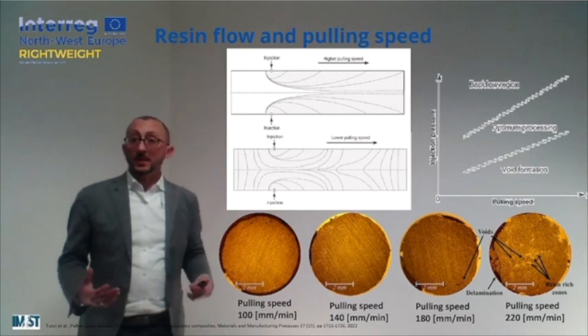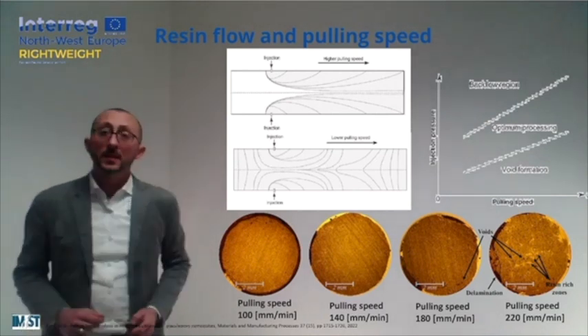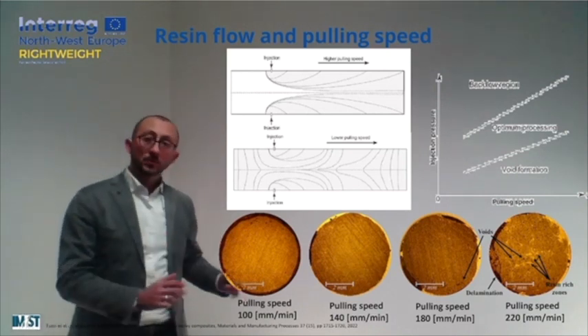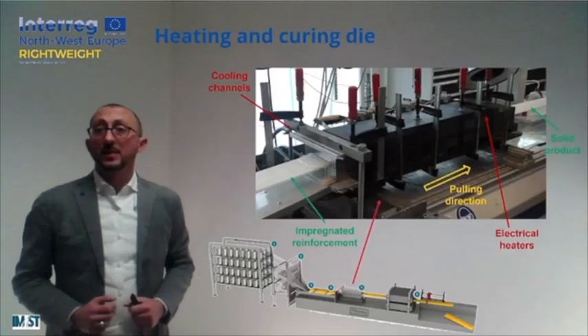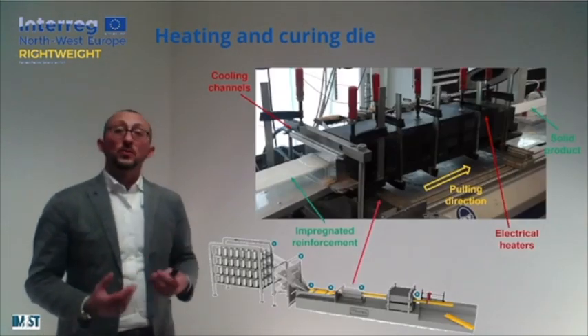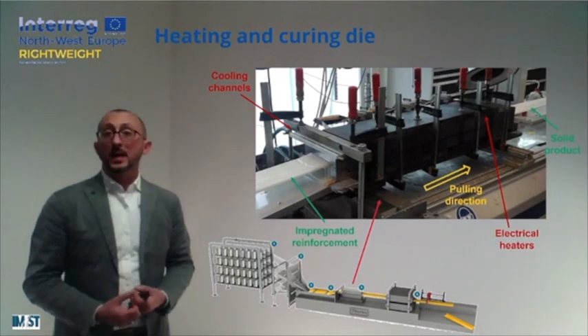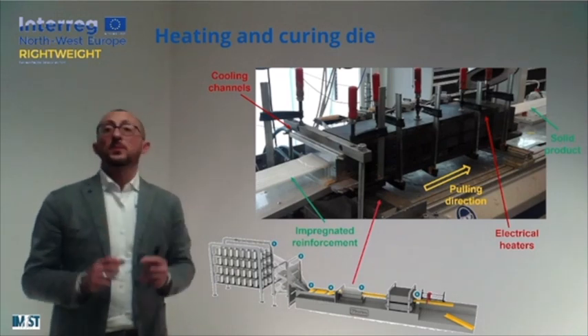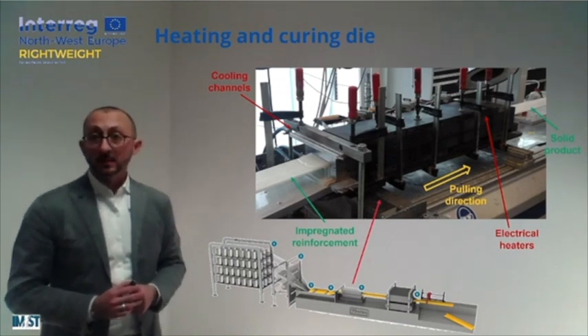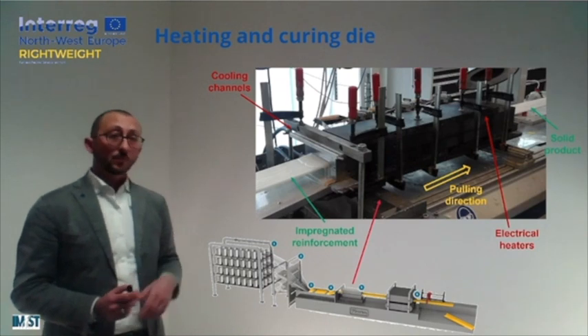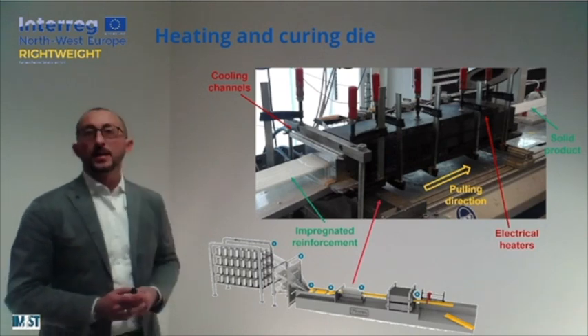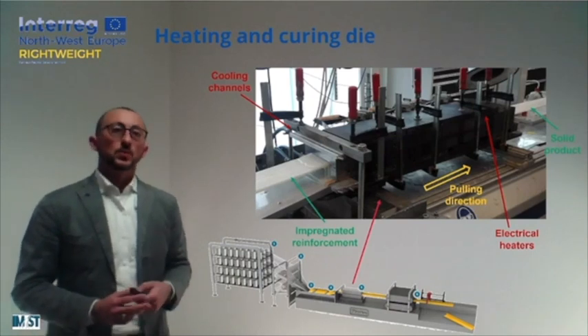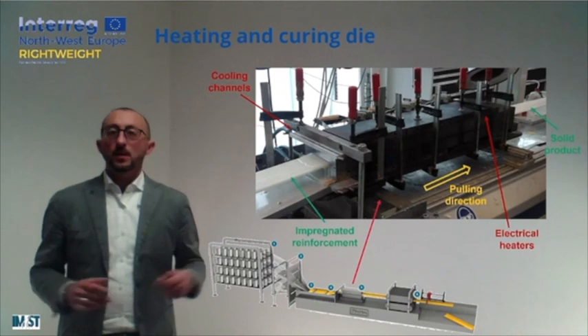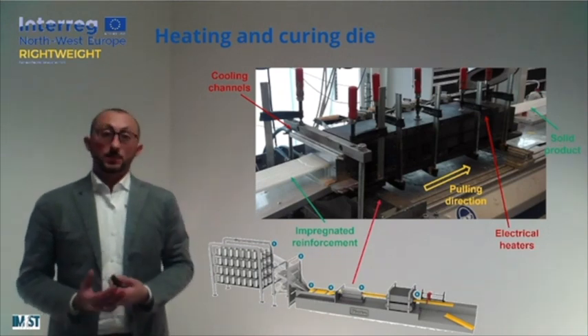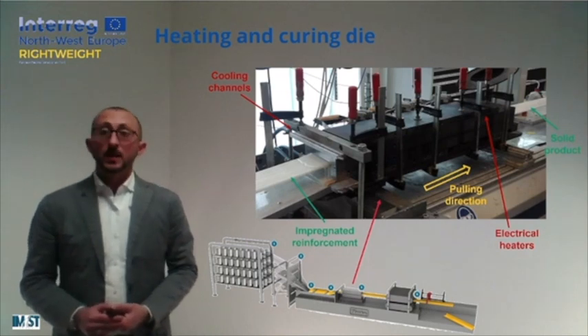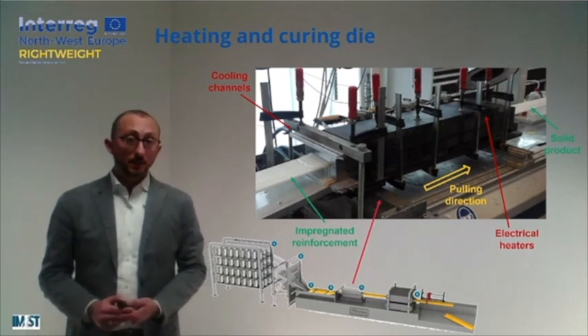So regardless of the system that we are using, it can be the open bath impregnation system or the injection chamber, after this combination, the material should be shaped and consolidated. And this is what is happening inside the core of our pultrusion line, and that is represented by the heating and curing die. On this figure, you can see a realistic pultrusion process. So the die is basically this steel block with an empty cavity inside that is providing the shape to our cross section. The die is realized using steel, and in order to